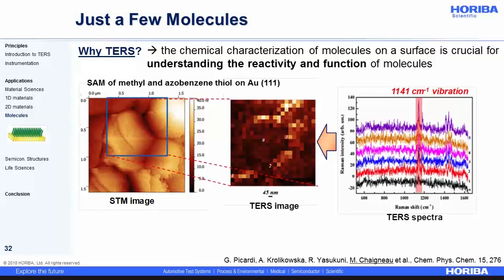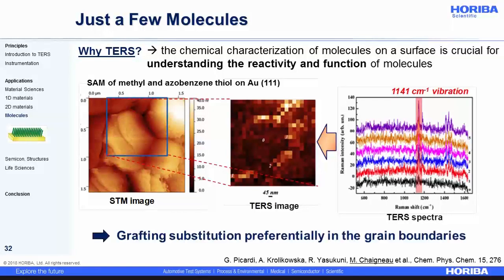So first of all, we are using an STM TERS tip in the present example to scan and to map the gold sample surface on the left, and then we perform a TERS map, a pixelized hyperspectral TERS map, in the square that you can see on this slide. And we can see clearly that the grafting substitution occurs preferentially in the grain boundaries of the gold surface. This is the kind of information, again, that is impossible to obtain with a conventional Raman microscope.